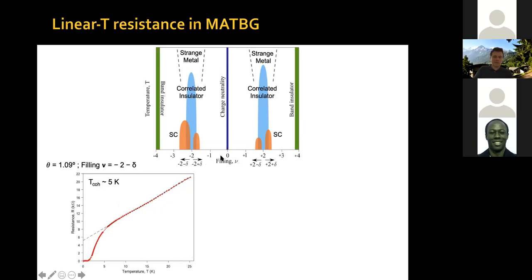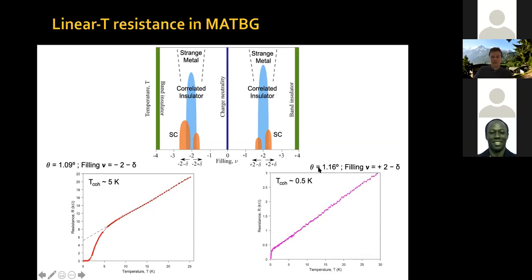It's linear quite a bit more in general, but these are extremely high temperatures for the system, because remember, this is a very low density superconductor material. So these are temperatures of the order of the Fermi temperature. It's the equivalent of going to several thousand Kelvin in other materials. Okay? You can take now a different device, at filling plus 2 minus delta, and this thing goes linear all the way to almost 0 temperature, right before the superconductivity sets in. This is for one of these small superconducting domes, okay?